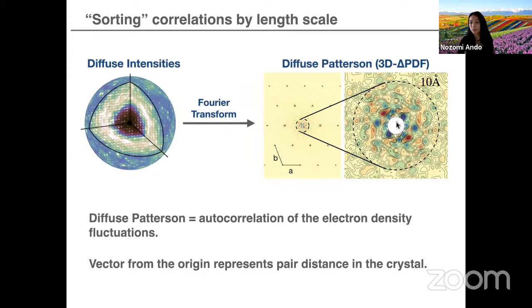So here we're looking at correlations below 10 angstroms, which is roughly the size of the protein. And this is a topology map. Blue is very negative, dark red is very positive, and we're seeing mountains and valleys. You can see that there are correlations that extend very far from the origin, past the size of the molecule and even past the size of the unit cell, which is what we would expect based on what we learned from lattice dynamics. The question is, how well did each of the simulations do?